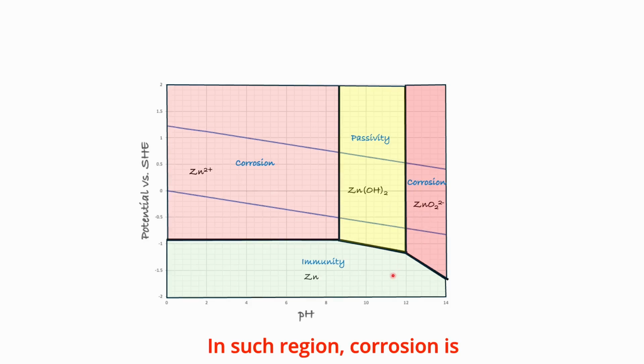In such a region, corrosion is thermodynamically impossible, and we call this region the immunity region. Conversely, if zinc metal faces conditions of pH and potential above these lines, the corrosion of zinc is thermodynamically feasible, as zinc 2+ becomes the stable species. At higher pH levels, corrosion becomes thermodynamically feasible, as zincate ions are the stable species under such conditions. Conversely, at intermediate pH levels, the stable species is zinc hydroxide. In this region,